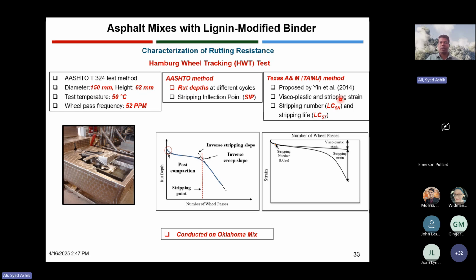Using this method, the viscoplastic strain and the stripping strain were separated, and then we also used 3 different parameters. One is the viscoplastic strain at the stripping number, which was used to evaluate the rutting. The stripping number was used as an indicator of moisture-induced damage, and the stripping life was also used as an indicator of moisture-induced damage. By the way, this test was done only on the Oklahoma mix.